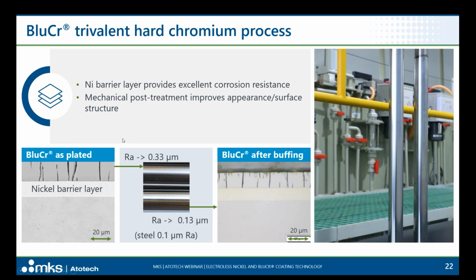On the bottom left side, you see the picture. This is the cross section of the steel part plated with nickel layer and BluCr layer on top. You can see that the nickel layer in this case acts as barrier layer. So in case of corrosive surrounding, you see that the layer is dense, it has no cracks, no pores, and this nickel basically is the reason why the corrosion protection, corrosion resistance is very high.